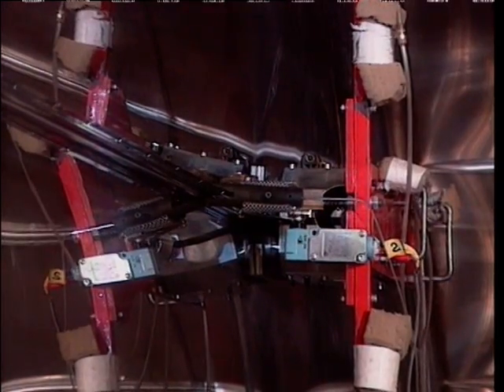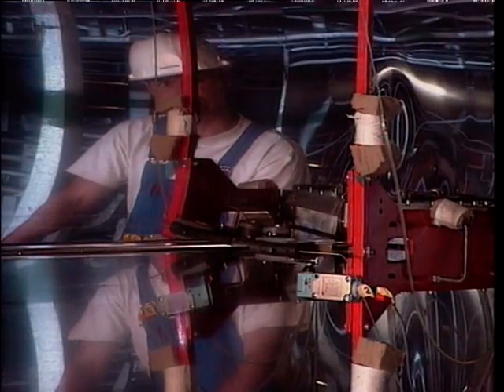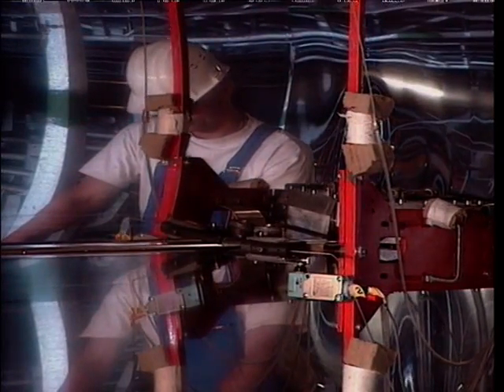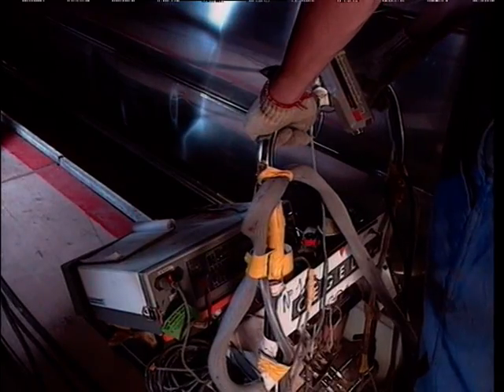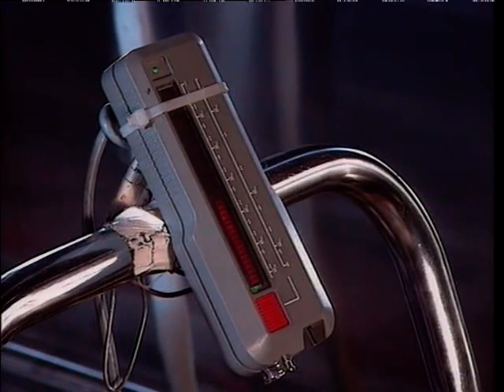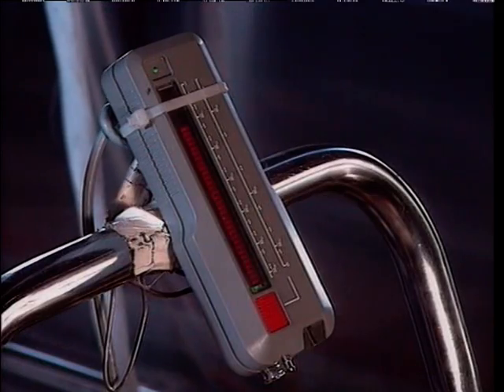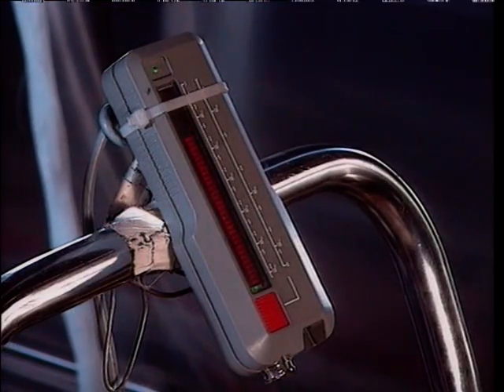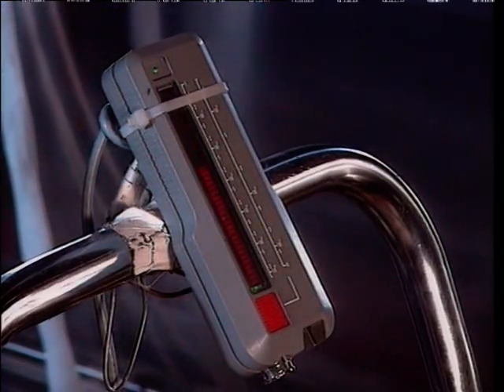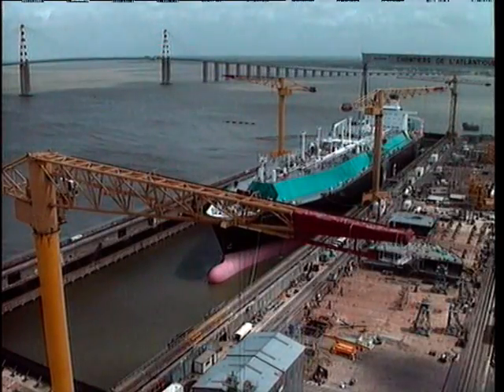This test is accompanied by a 540 millibar initial vacuum pressure test to check the overall quality of the tightness. At the end of these controls, the secondary insulation and membrane are complete. These operations will need to be repeated for the primary insulation and membrane.